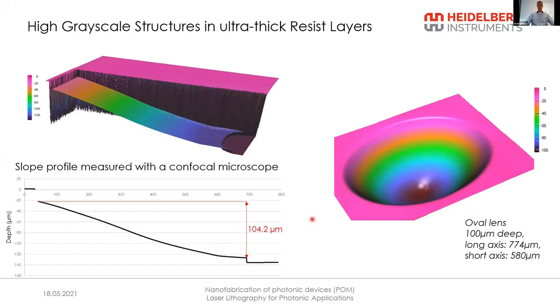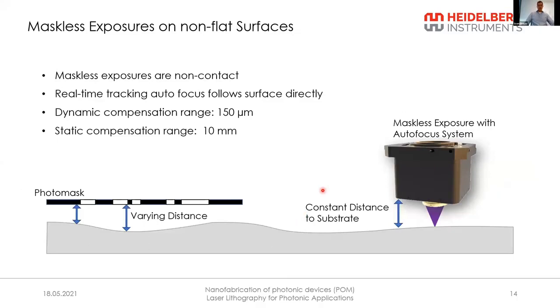And we know there's quite a number of people interested in this kind of thickness. Another advantage of this maskless exposure technology is that it's a non-contact exposure process. So when you have a substrate that's not completely flat, if you use a photomask, you have the problem that across the photomask, the distance between the photomask and the substrate will vary. And this will translate into the patterns that you're exposing. So varying distance will change the width and the uniformity of the patterns, and it's very difficult to achieve good exposure quality across a substrate that's not uniform.